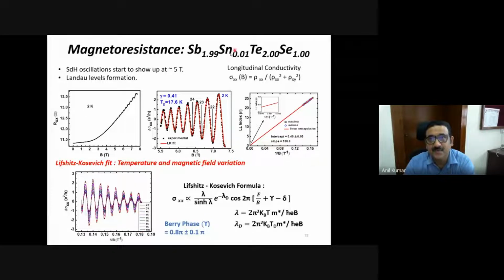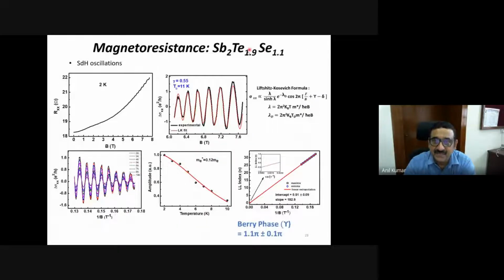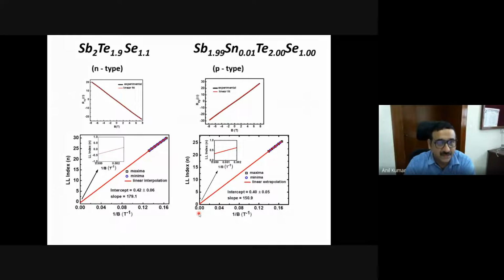This is tin doped antimony tellurium selenide. And now if I remove the tin doping, still I have these oscillations. And again, I have this pi Berry phase. This tells me that this is a topological material, right? So this topological material has got surface state which is conducting, and the bulk can be insulating.